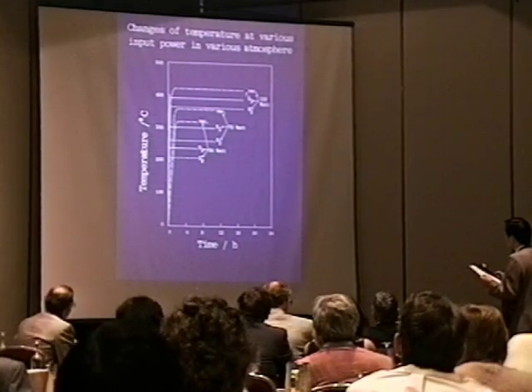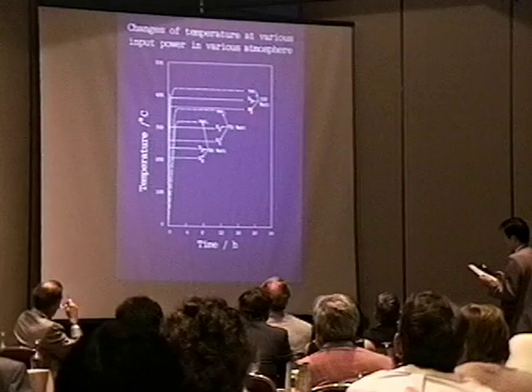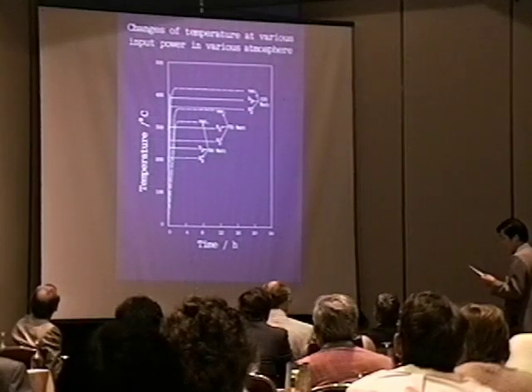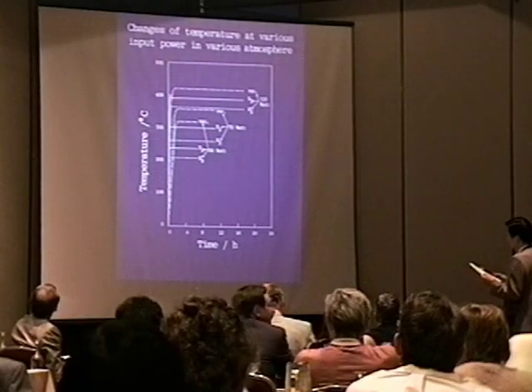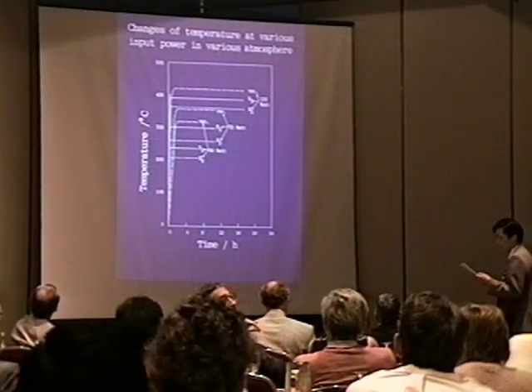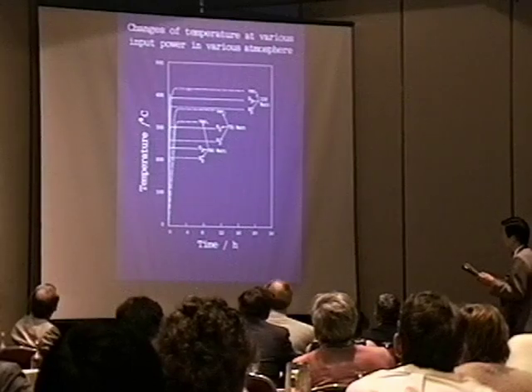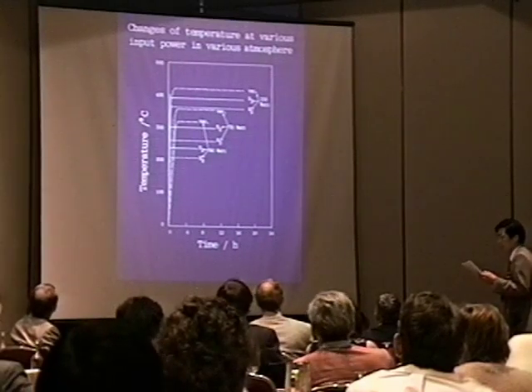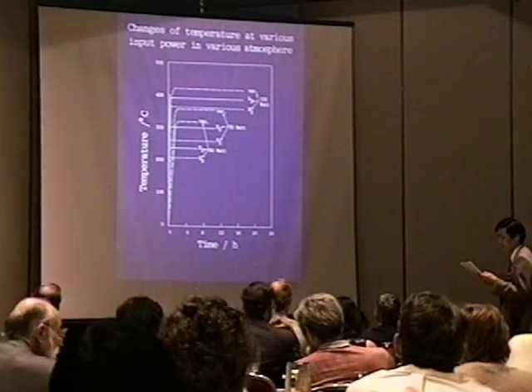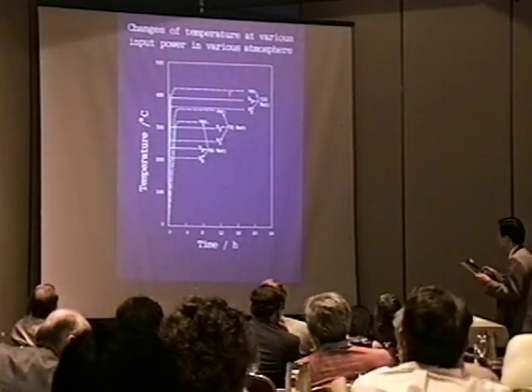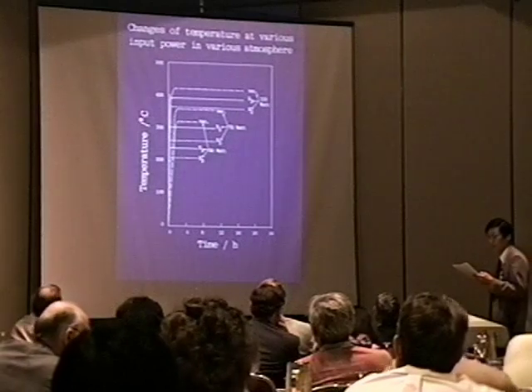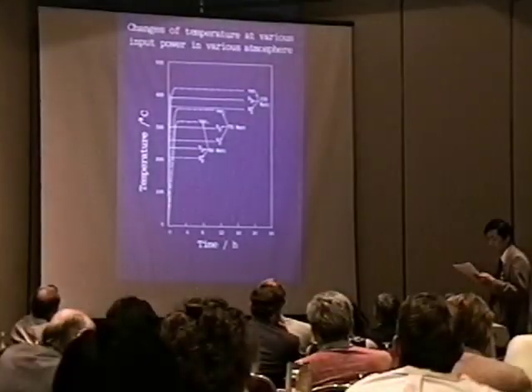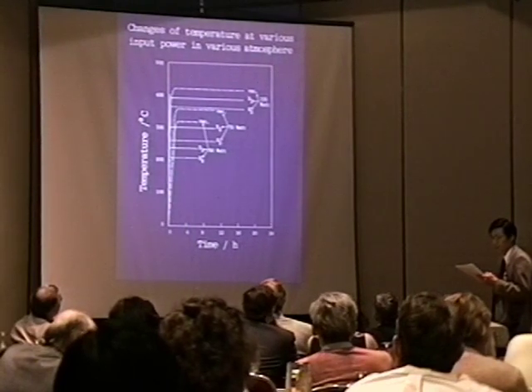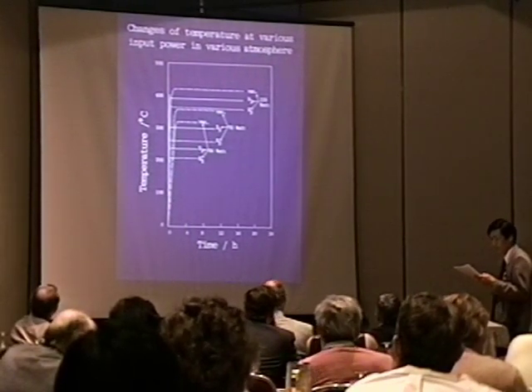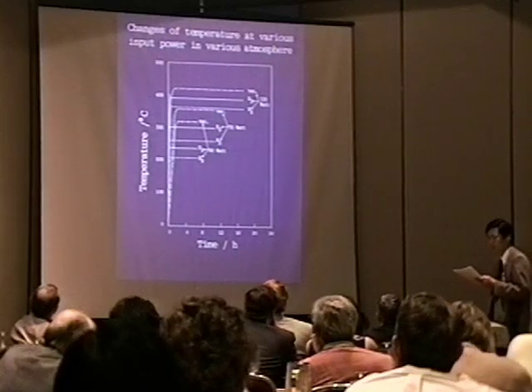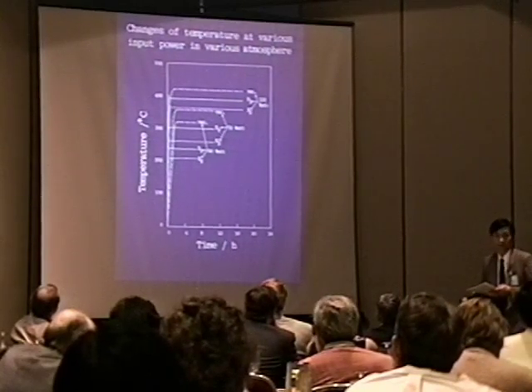In vacuum, and in deuterium gas and hydrogen gas atmospheres, temperature rose steeply after switching on the electric power and reached a constant temperature within 2 hours. Temperature differences between each atmosphere are caused by the heat conductivity difference. The pressure of hydrogen and deuterium was 0.1 atmosphere, but temperature was not much dependent upon the gas pressure. Next slide.